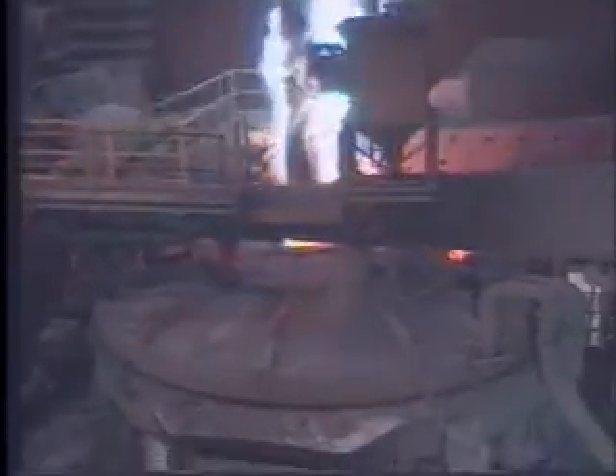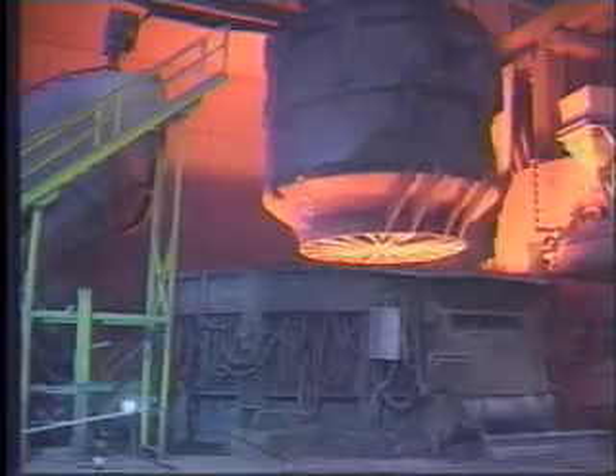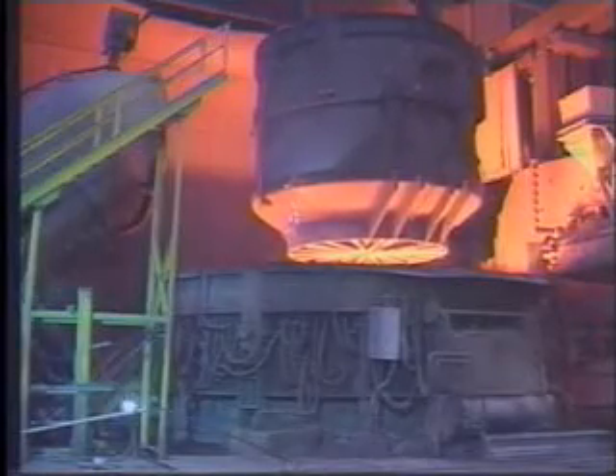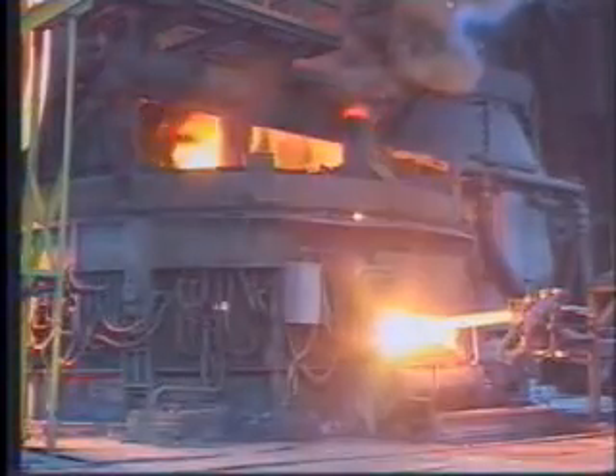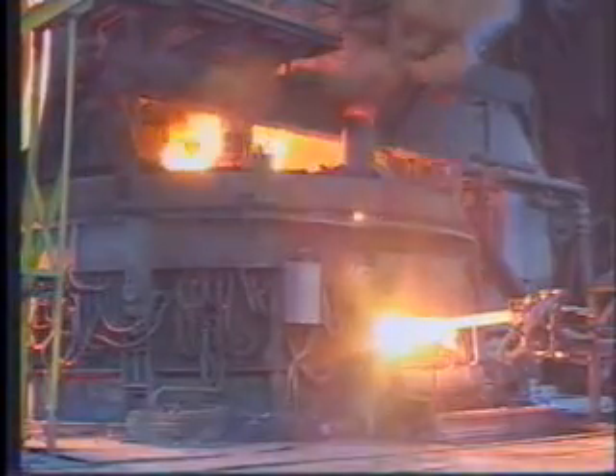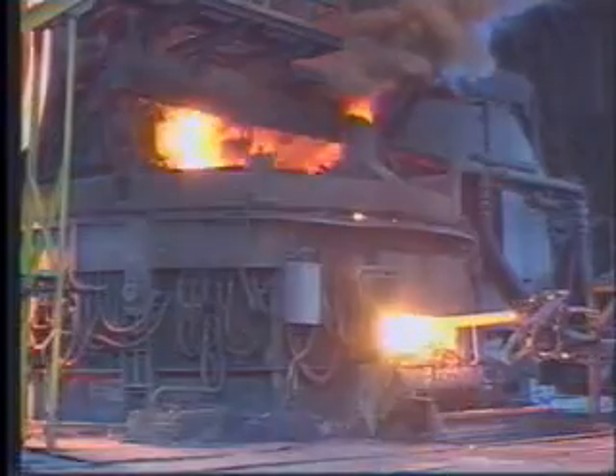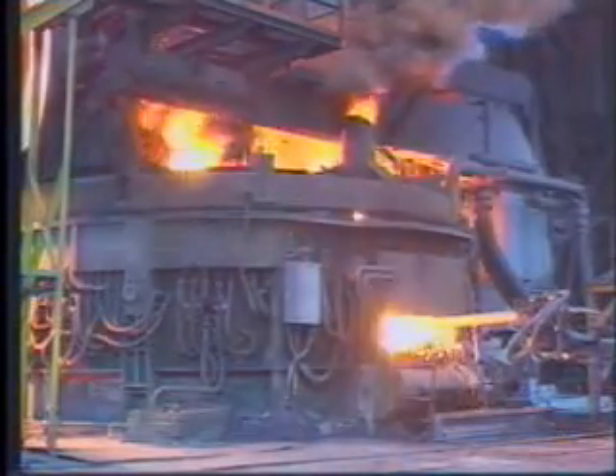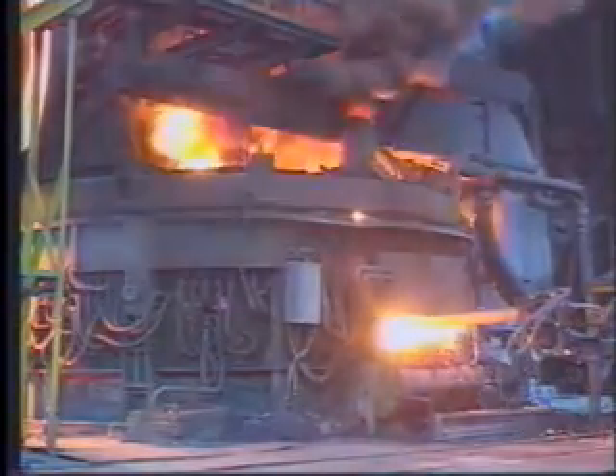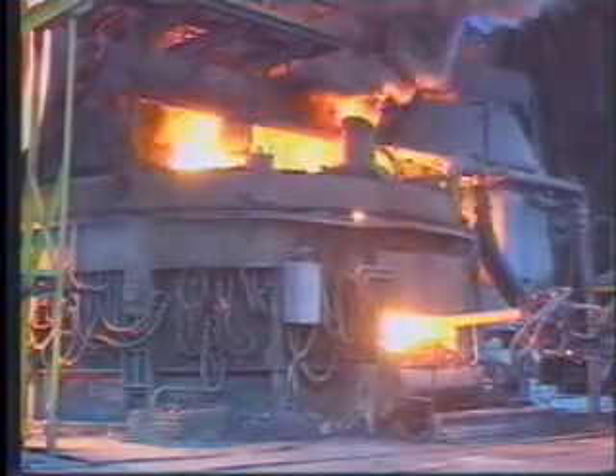The electrodes are lowered until they form an arc. This electrical arc generates the heat used to melt the scrap. This is repeated until the needed amount of steel has been added. It takes approximately 2 hours to completely melt the heat of steel. Each heat is roughly 360 tons. During the melting operation, an oxygen lance is used to supplement the heating process.